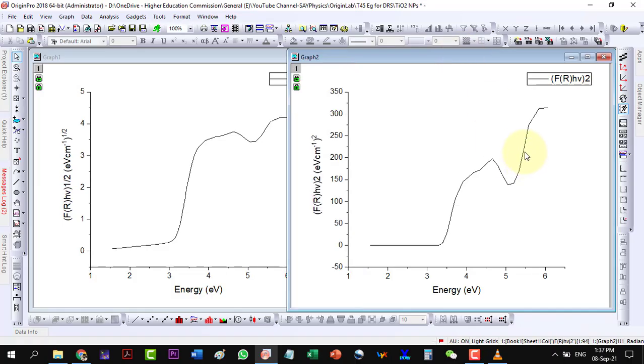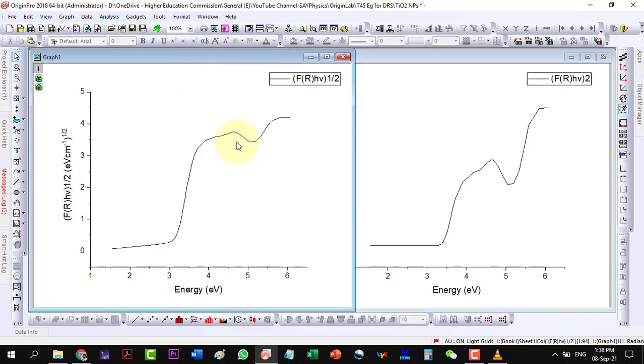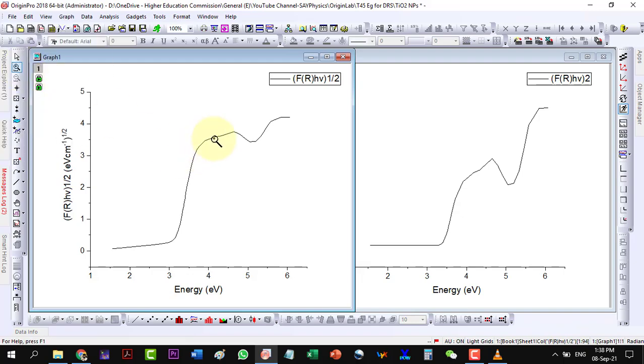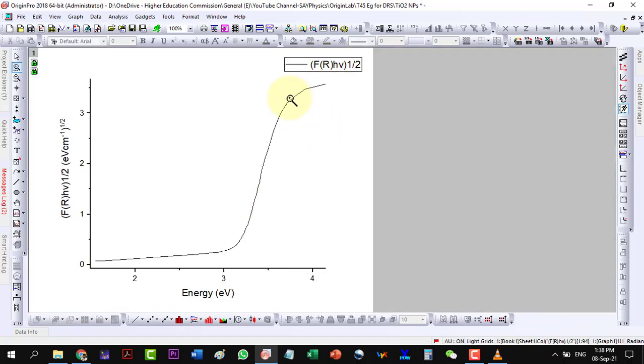It is evident that there is a possibility of having both the direct and indirect bandgaps, that is, the bandgap is having a quasi-direct bandgap character. The possibility of the indirect bandgap is comparatively more prominent. So let us calculate this one. By extrapolating the linear region onto the X axis gives the bandgap energy close to three electron volts.